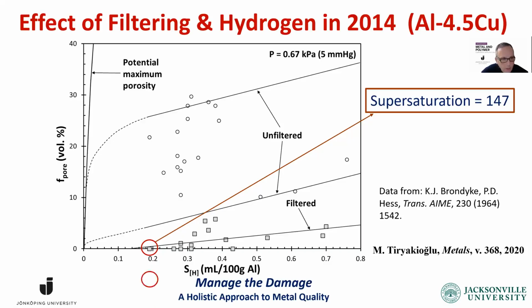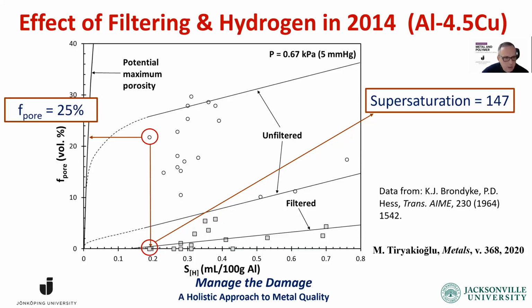If you compare it with this one, same hydrogen level, you get about 22% porosity when it's unfiltered, when it's damaged. So that is the effect of filtering. That's the effect of getting rid of the oxide films that come with the skin of the ingot, the skin of the rejects, the skin of the gating system that you put into the melt. All the damage caused by the rotary degas, when you get it out, that's what happens.